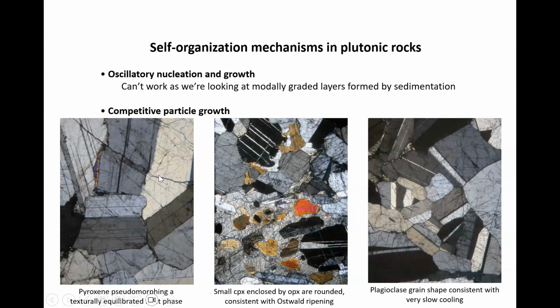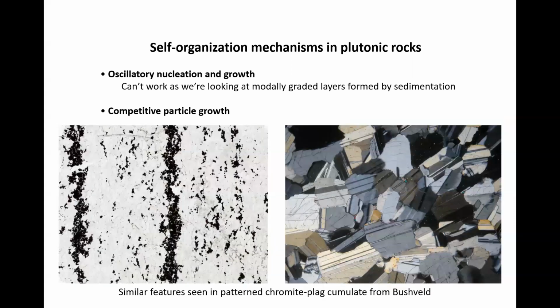And the other thing, which is really nice, is that when you see the clinopyroxenes that have been enclosed by later crystallizing orthopyroxene, the smaller they are, the more rounded they are, like these ones here. So that's the other signature for Ostwald ripening, because as grains dissolve, they become rounded. So the small ones are rounded and the large ones are more euhedral. That's absolutely the key indicator for Ostwald ripening. So we've got all the evidence there to record this sort of activity of competitive particle growth for this microstructural self-organization.